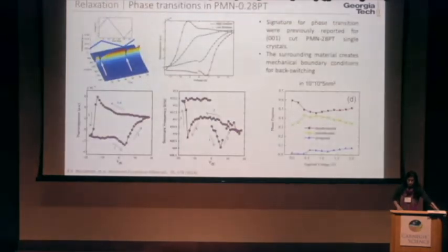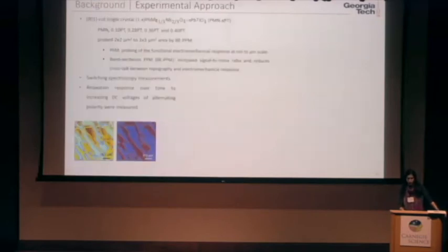And we can actually track through the contact resonance frequency any eventual phase transitions that happen under our applied electric field, and that results in a very large softening of this resonance frequency, corresponding to this enhanced electromechanical response. So as you can see, this is the red curve with respect to a regular ferroelectric transition within the same material. So what we are proposing to do in this work is actually look a lot more coherently across the phase diagram at what happens in these materials.